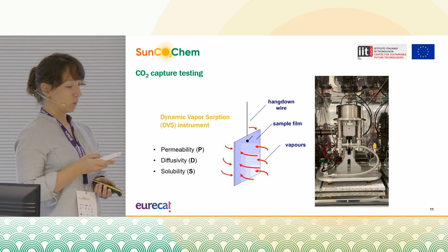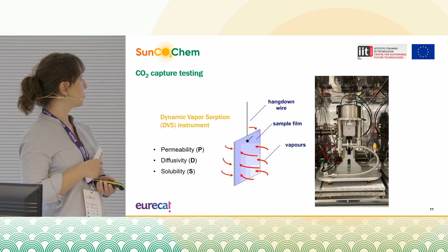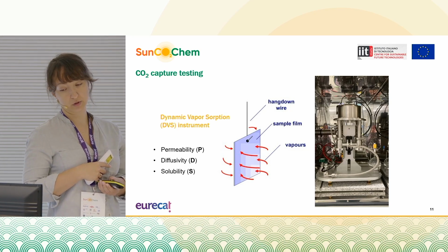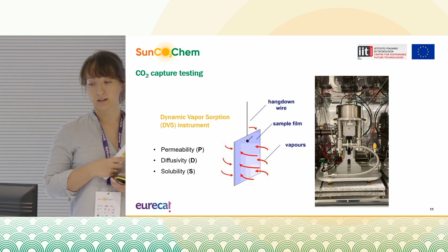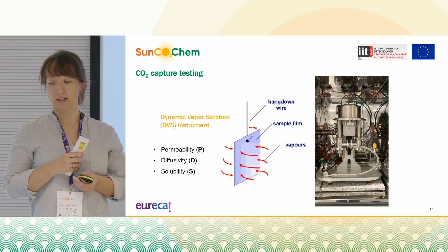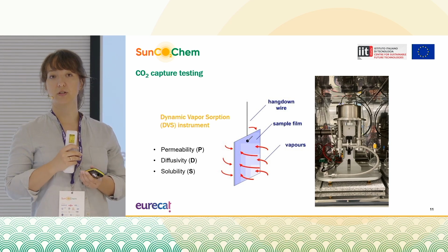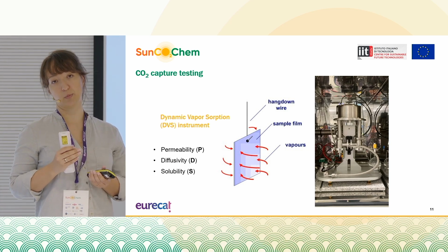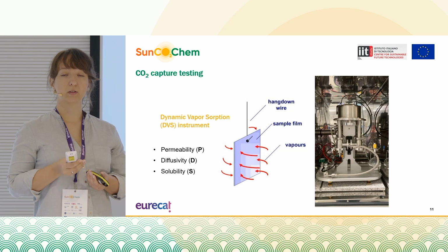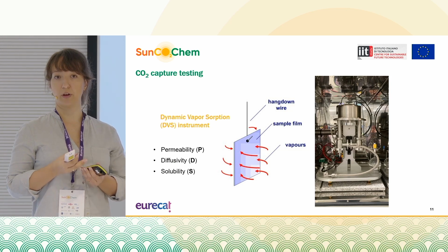These membranes were tested for the CO2 capture in a dynamic vapor sorption instrument, where basically we hang our sample in the chamber, we charge it with gas at a specific pressure and temperature, and we measure the change of the mass of the membrane.